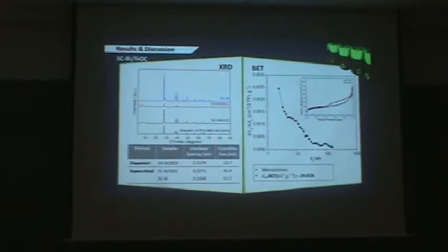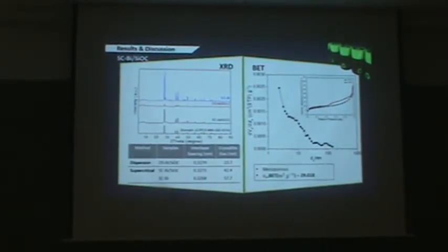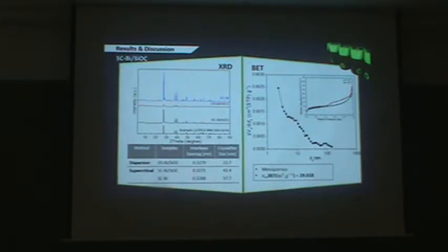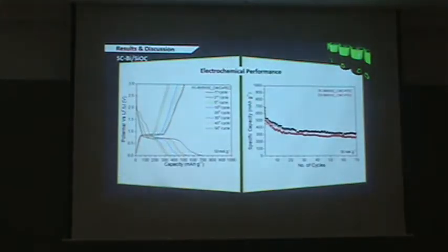To prove that the nanostructuring of our method is very good, we produced bismuth silicon oxycarbide using a simple dispersion method, which means that we dispersed the bismuth precursor into silicon oil. As you can see, even though the crystalline size is quite low, which is 23.7, the electrochemical performance is low compared to the method that we use with supercritical fluid.